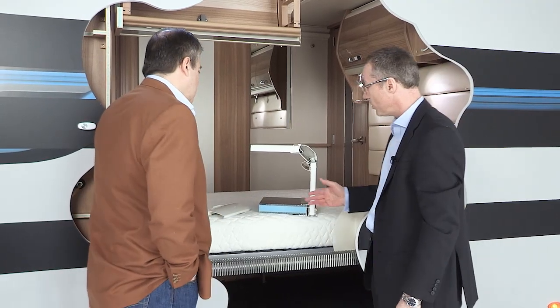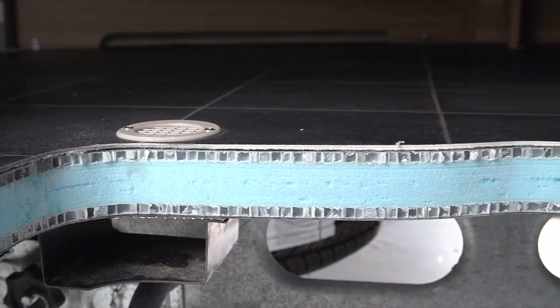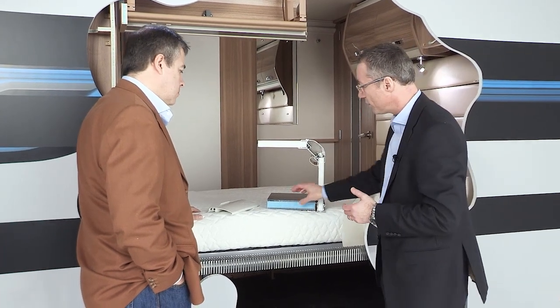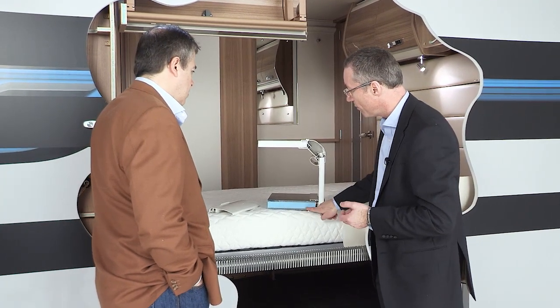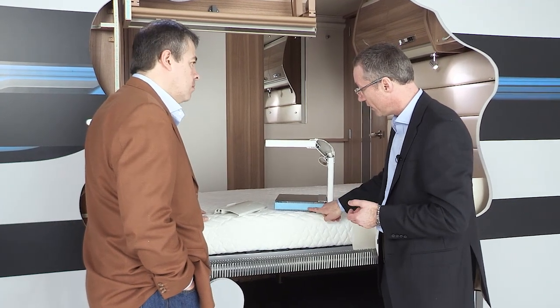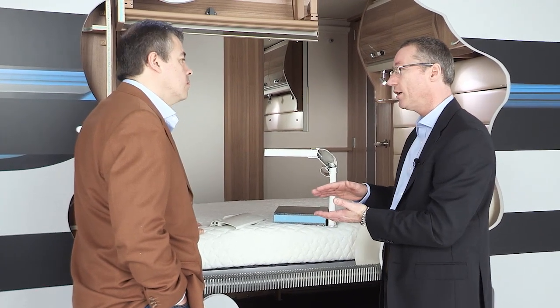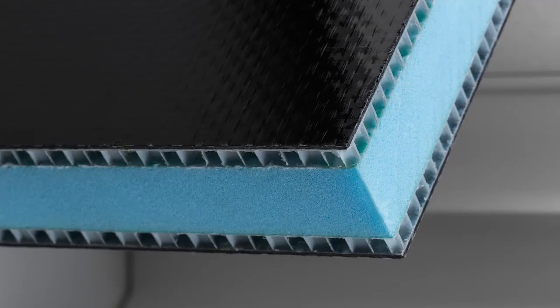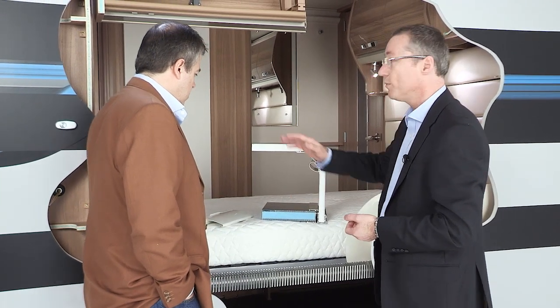This black area is the floor. The next challenge was to come up with a strong and thermally efficient floor. We ended up building a five-laminate floor system that builds upon the strengths of each core material. We start in the centre with a very thermally efficient expanded polystyrene core, which is then sandwiched between two layers of plastic honeycomb material that have immense strength. And then on top of that, a woven GRP surface — you can see how it's woven in the surface there, which gives it its extra strength.